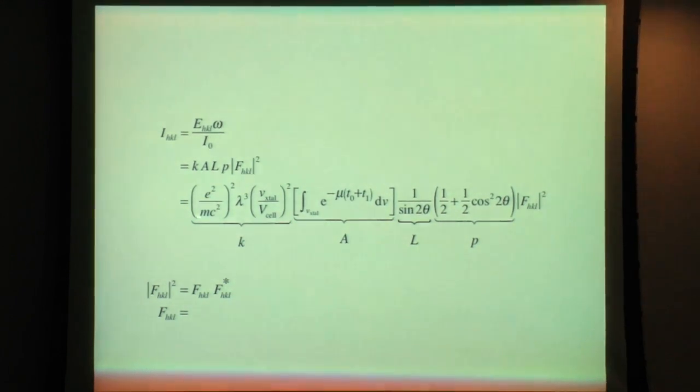Here's the Thomson scattering for a single electron. Here is the cube of the wavelength. Here is the ratio of the crystal volume. How big a crystal are we scattering from? And we're assuming, for simplicity, that the crystal is of a size such that it is bathed in a uniform incident beam. So it's smaller than the diameter of the incident beam. That's a simplifying assumption, it isn't a required assumption. It can allow for crystals that stick out of the beam and so on. The crystal volume divided by the unit cell volume, that quantity squared, then this absorption factor.